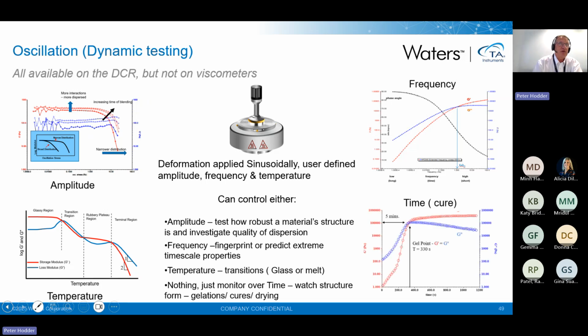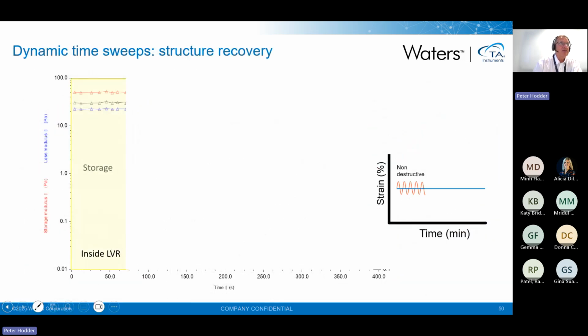And we can see in this example a full cure of a material like a 2-pack epoxy glue or super glue. And for those who are in the coating industry, whether it's topicals, creams and lotions, or paints, inks, or anything else like that, you should be interested in being able to probe the structure of a sample at rest, to see how structured it is. G prime is red, so that's solid dominant because it's greater than the blue line here. So if we look at the material, the red is greater than that, and the viscosity is here.